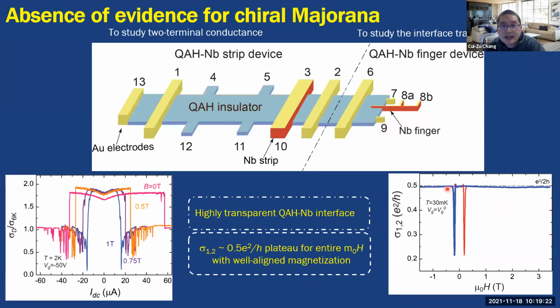So we also did this experiment in 2009, and this is our device. This device includes 2 parts, and this part is actually quite similar to this kind of part, and we put a Nb strip here, and this is a Hall bar. We could measure the 2-terminal resistance to check whether it shows this kind of half quantized plateau or not, and to see if that half quantized plateau is indeed related to the chiral Majorana. This side we call the quantum anomalous Hall Nb finger device. We put a very narrow Nb finger here. We want to do the Andreev reflection measurement to check the transparency between the quantum anomalous Hall and superconductor layers. We performed the Andreev reflection measurement and confirmed the transparency between quantum anomalous Hall and superconductor Nb finger is very good in this device.